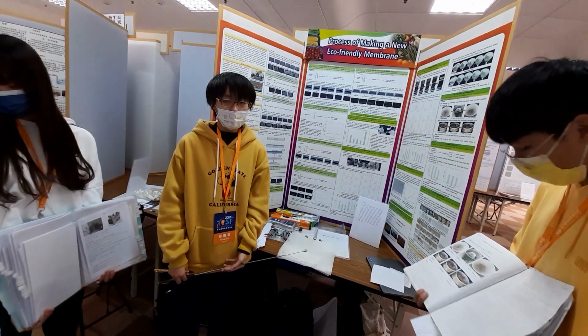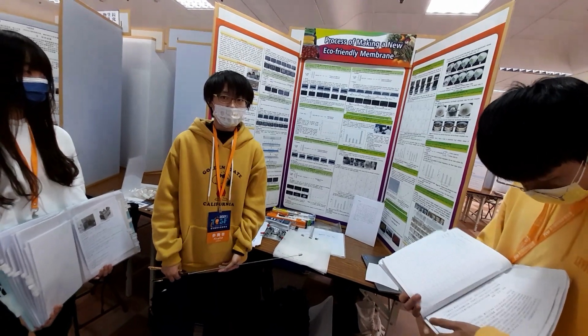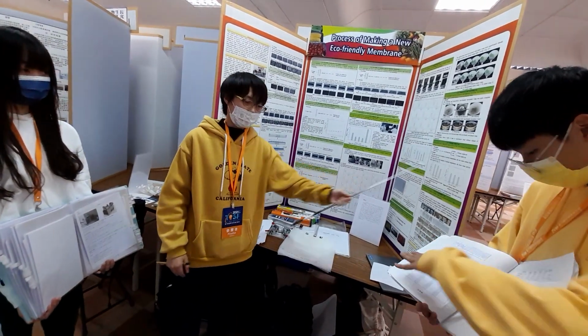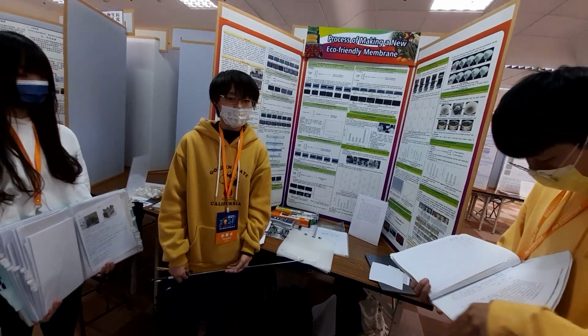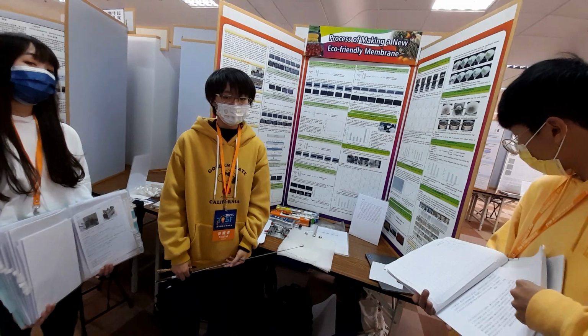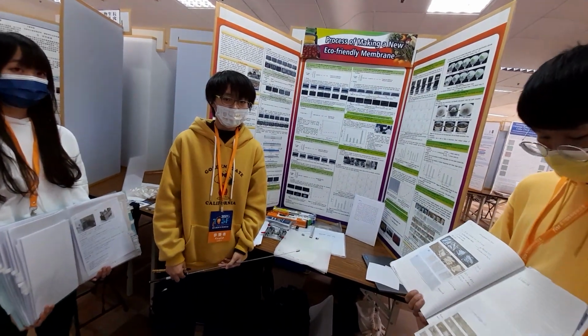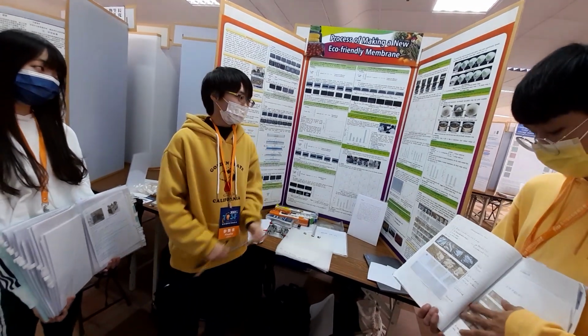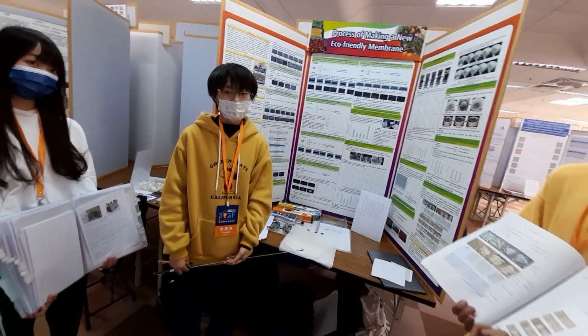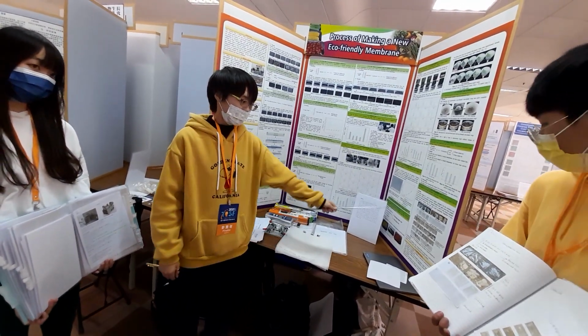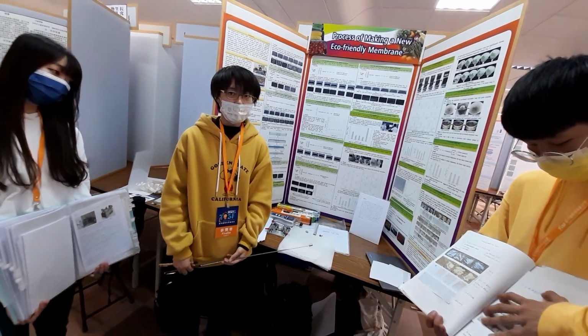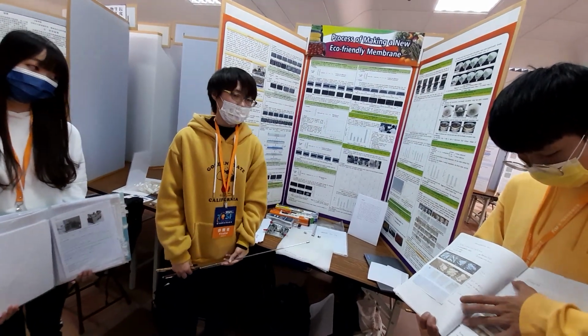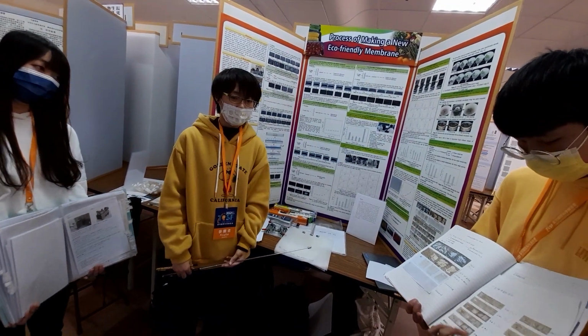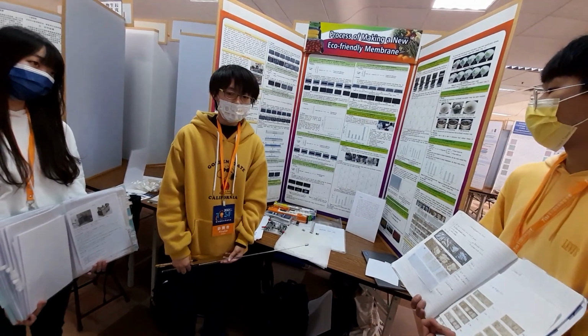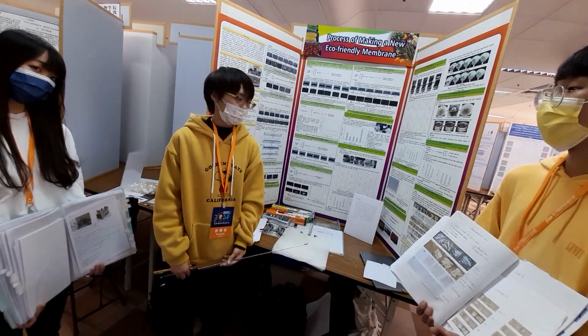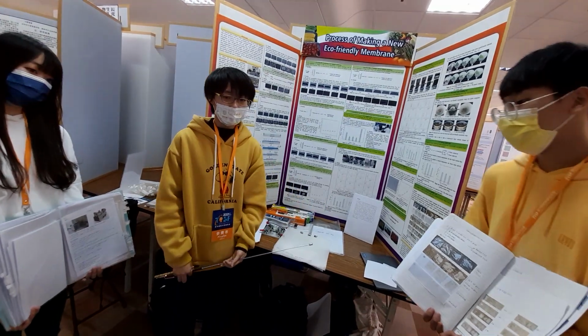The eco-friendly non-plastic wrap had good storage ability. The water content and water activity of it will gradually increase through time passing. The water activity of it was all less than 0.6, which prevented the growth of microorganisms. We did the corruptibility test to see whether it was eco-friendly or not. The result was satisfying because after 21 days, our wrap could not be seen, while commercial plastic wraps will still have the complete appearance. So we proved that our wrap was an eco-friendly product.